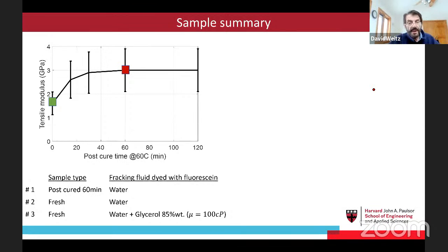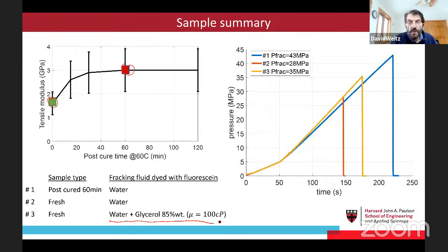What we did was we prepared two samples. Remember, I told you that if we cure the sample, we can change its modulus by roughly a factor of 2. So I can show you a softer and a harder, or stiffer, sample. And we also used a more viscous fluid to slow the fluid down. And I'll show you the behavior of all three of them. And now to show you what we can do.